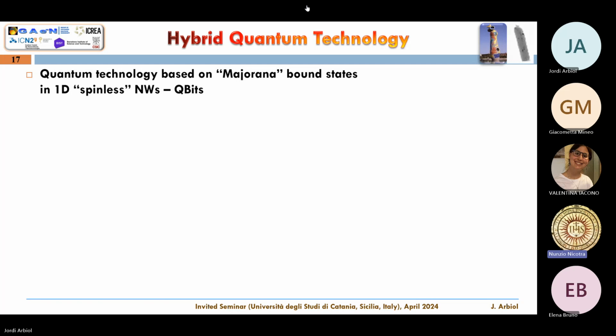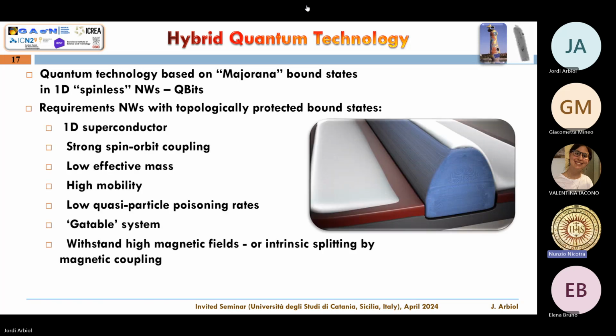First of all, what you need is a one-dimensional spinless nanowire. And for this, what will you need? You need a one-dimensional superconductor. I was talking about a semiconductor, okay? But here appears the word superconductor. So you need a strong spin-orbit coupling. That's another of the things you need. Low effective mass, high mobility. When I'm talking about high mobility, you think about what I said before, indium antimonide, indium arsenide. So that is the semiconductor part.